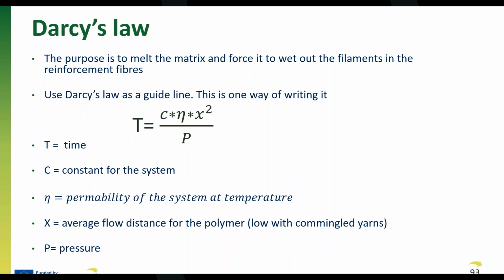The time depends on the system you're actually working on, but it's mainly the permeability of the system at the temperature working at, the polymers and so on. But what's important is to know that the distance the polymer has to flow squared is a very important thing, and that's why we are using commingled yarns here, because then you are getting a very low distance that you have to move the polymers. And then you see the higher pressure you put on, the faster it will go as well. But that's only linear to the pressure. So those two are the most important things when you have chosen your system.